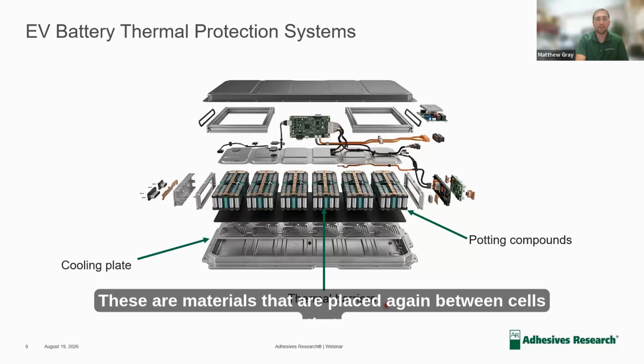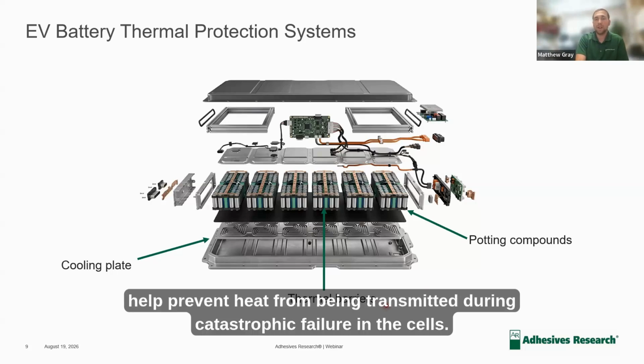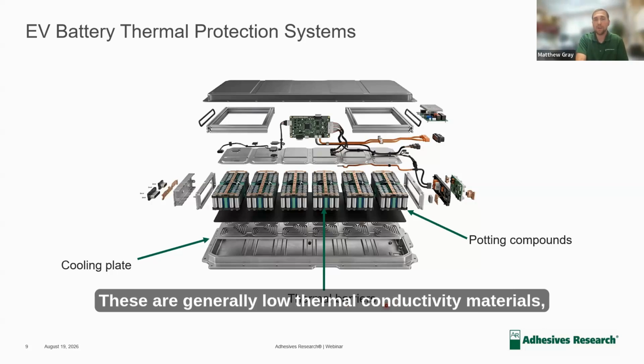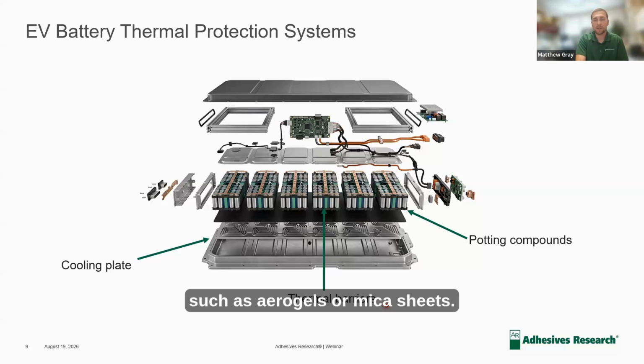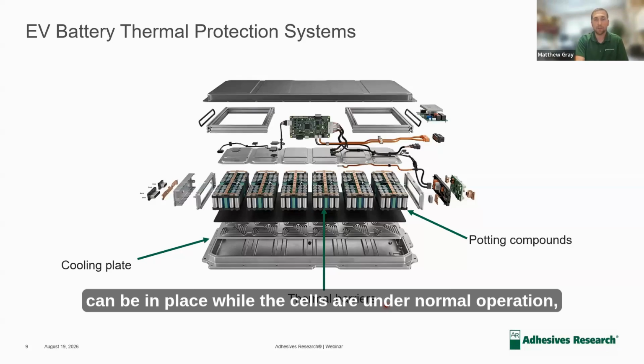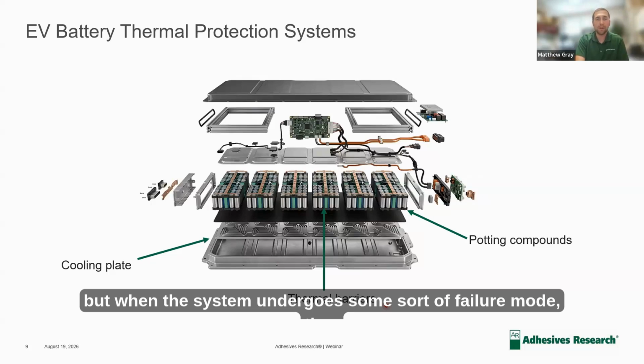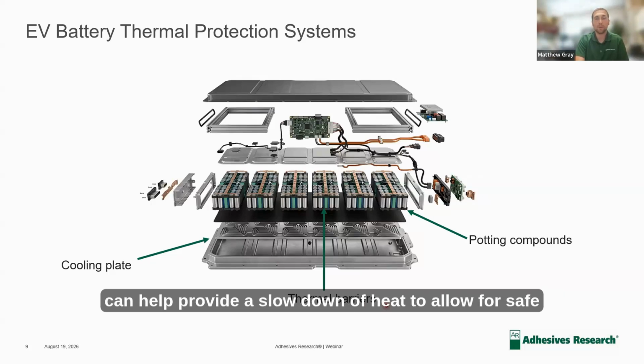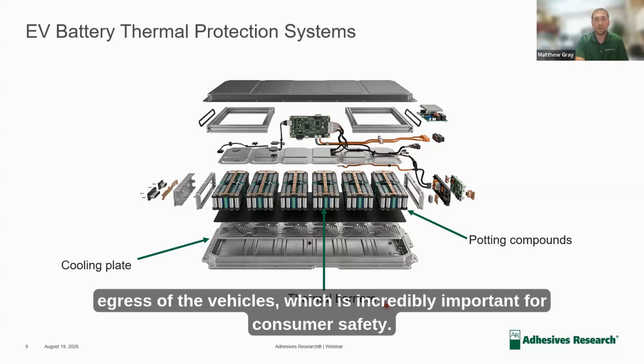These are materials that are placed, again, between cells that help prevent heat from being transmitted during catastrophic failure in the cells. These are generally low thermal conductivity materials, such as aerogels or mica sheets. And the benefit here is that they can be in place while the cells are under normal operation, but when the system undergoes some sort of failure mode, they can help provide slow down of heat to allow for safe egress of the vehicles, which is incredibly important for consumer safety.